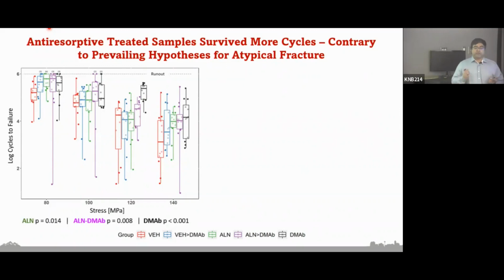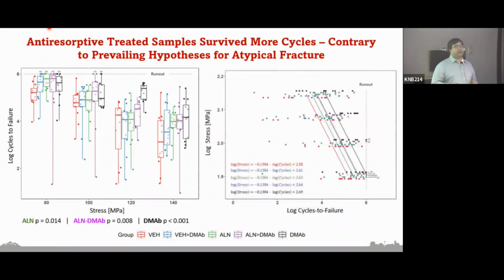Statistically, we saw it was 12 months of alendronate followed by DMAB, or DMAB alone, that had statistically higher fatigue life. But that trend, I think, is a little bit clearer if we plot the data in something that looks like this. So this is just the same data. It's just plotted on a log-log scale with stress on the y-axis. And the solid lines here are the result of a survival analysis fit of the data.